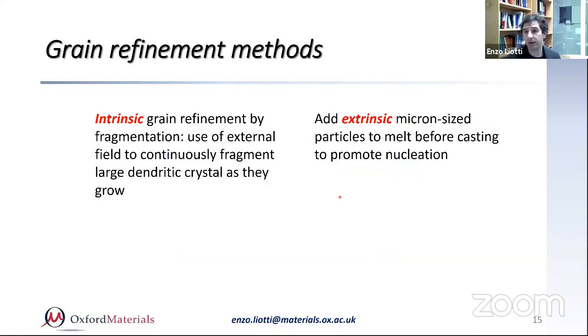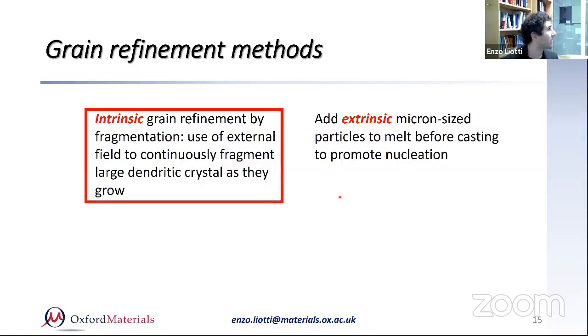To grain refine an alloy, you can use an intrinsic method, such as grain fragmentation. It is intrinsic because you are not adding anything to the material, but essentially using an external field to continuously disrupt the growth of the columnar dendritic array. The disruption and breaking of these arms will generate new crystals as they grow and grain refine the material. The extrinsic method instead is when you add micron-sized particles to the melt to promote nucleation. A typical case in aluminum is the addition of TiB2. The first example would be regarding intrinsic grain refinement.